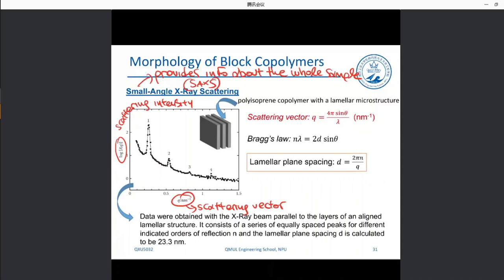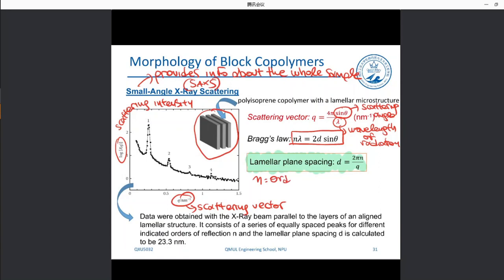The scattering vector is a function of the scattering angle. And this is the wavelength of radiation, which is going to be constant. It's going to be set by the equipment. So if we combine this with Bragg's law, which is this very simple equation, we obtain the lamellar plane spacing, which essentially gives us, if we have a lamellar structure like this one, the spacing between the two lamellas. So this d is equal to the ratio of 2πn over the scattering vector, and n is the order of reflection.